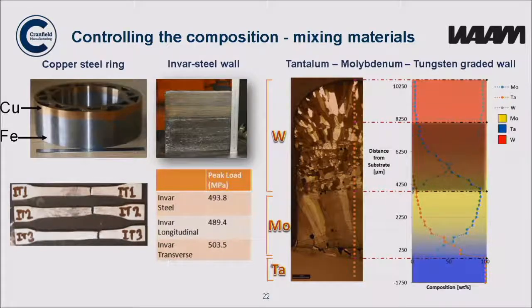In this case, we started off with tantalum, then we go through molybdenum to tungsten. This is, of course, for nuclear applications for the plasma screening systems, but nicely demonstrates how we can swap. Tungsten doesn't have very good mechanical properties, whereas tantalum does. So we put down this graded structure, and then we can make an area that has high neutron screening, but attached to a substrate that has high mechanical properties.